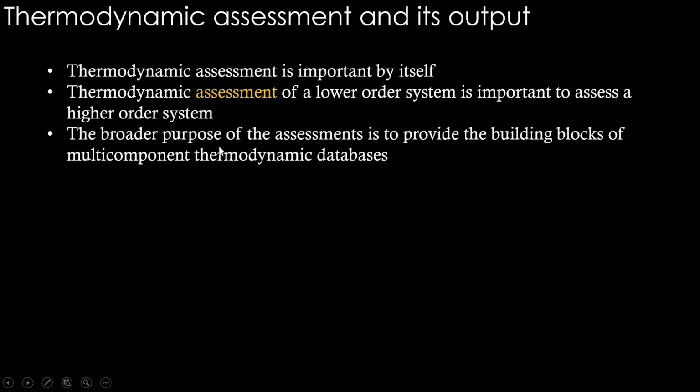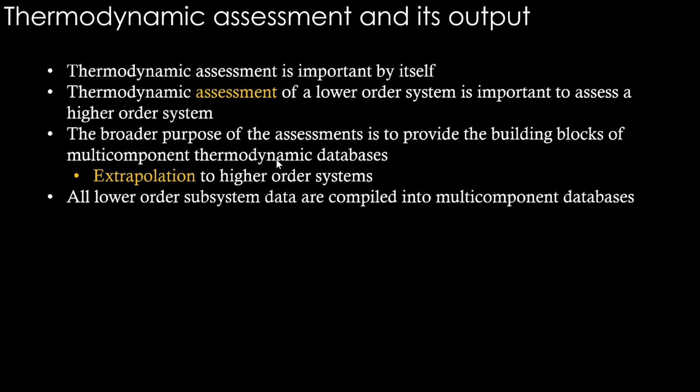And then another broader purpose of the assessment is to provide the building blocks of multi-component thermodynamic databases. These are the commercial things that I have been talking about, where multiple subsystem data are combined to form multi-component databases. And extrapolation to higher order systems happens here because most of the data is for unary, binary and some ternaries. Let's say 7 component or 12 component kind of systems. For them, again, calculation can be done using extrapolation from this lower order system data. So all lower order subsystem data are compiled into multi-component databases.